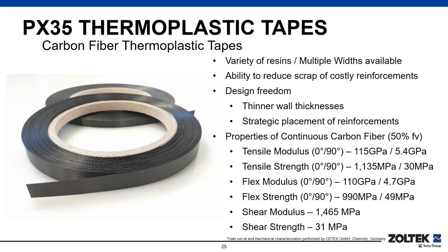The use of carbon fiber reinforced tapes allows for design freedoms like thinner wall thicknesses, designing in lower performing or cost-effective resins, designing in or removing of features like bosses and ribbing, since the primary part structure will be increased in property performance with the use of continuous carbon fiber tapes. The placement of these continuous reinforced tapes enhances the overall performance of the component or injection molded part. The finished part will have a combination of enhanced properties that are more in line with carbon fiber reinforced tapes. These typical properties of those tapes are a tensile modulus of 115 gigapascals, a tensile strength of 1,135 megapascals, and a flexural modulus of 110 gigapascals.